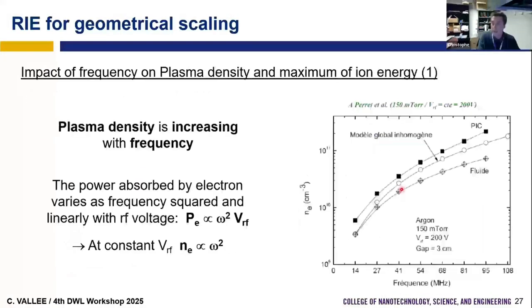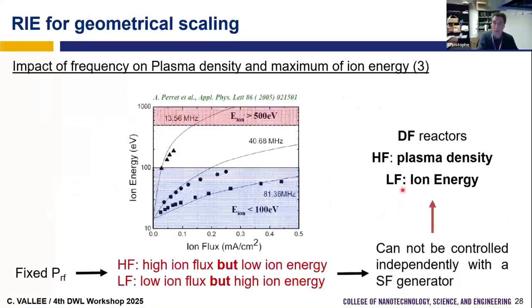So we can see we have two opposite behaviors of ion flux and ion energy with frequency. High frequency: more dense, but less energetic. Low frequency: less dense, but more energetic. So this is what we have, for example, for a fixed power applied to the substrate for a single frequency plasma etching process. If we use a high frequency generator, for example an 80 megahertz generator, we'll have a high ion flux.